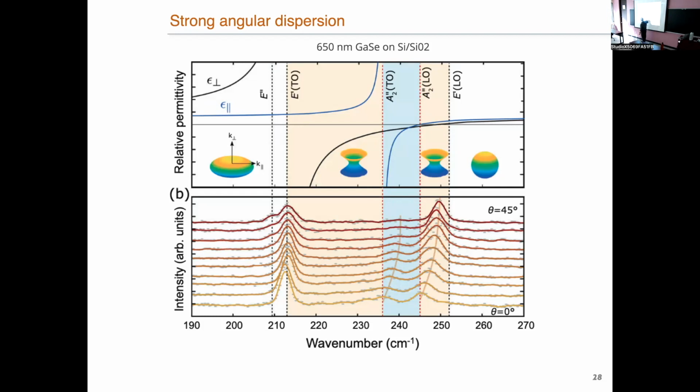So in this region, we always use the other main phonons, this A1 that's right here, totally symmetric, that shouldn't move. Another one that's right here that shouldn't move as well, as a calibration. Here, there are two difficulties that appear. First, we should expect polaritons in this region, but we couldn't assign with certainty anything going on there. But this polariton, which is of group symmetry E prime, is expected to move with the angle because we have an anisotropic material.